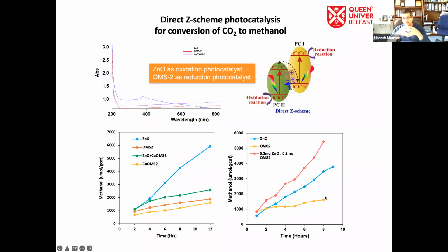So by tuning the metal oxides, by combining them in the Z-scheme format, and by using the right kind of reactor where you can shine two light wavelengths at the same time, you can produce much higher quantities of methanol and achieve much faster reaction rates. So that's definitely both band gap engineering as well as reaction engineering. This is material science as well as designing the proper reactor to achieve high efficiency in this kind of reactor.